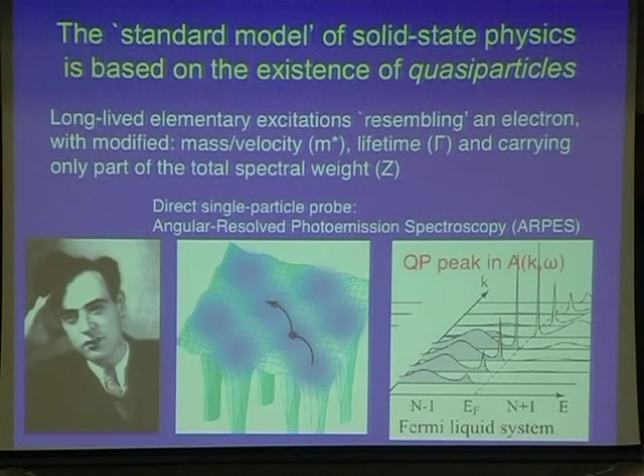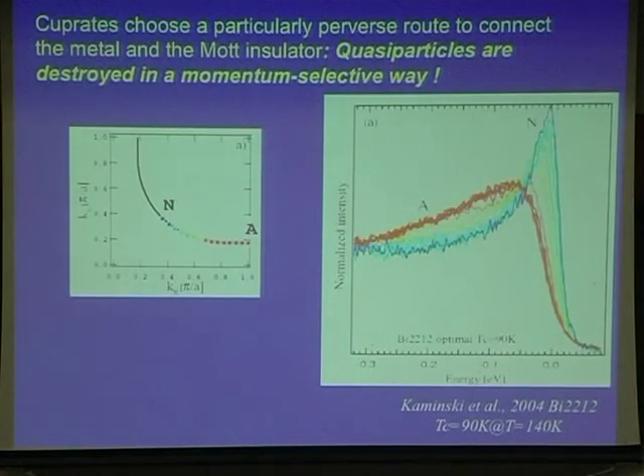These quasi-particles can be detected by beautiful spectroscopic techniques, which Atsushi is a pioneer of, so-called photoemission spectroscopy. And when there is such an excitation, you see it as a peak in this photoemission spectrum. Now look at what copper oxide superconductors do. This is measuring the photoemission spectrum of a copper oxide metal, going from the so-called nodal position on the Fermi surface to the so-called antinodal position close to the boundary of the Brillouin zone.